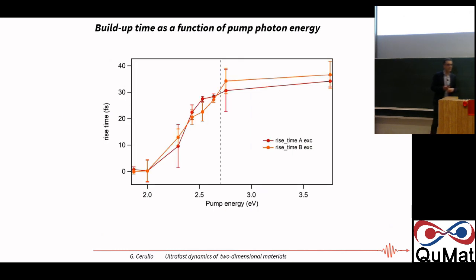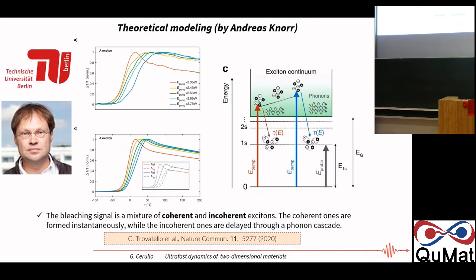So we can really make a graph of the build-up time of the exciton bleaching as a function of pump photon energy, and we see that it rises until it nearly saturates at something around 30 to 40 femtoseconds. So to understand this, we asked for the collaboration of the group of Andreas Knorr in Berlin, who modeled our experimental results, considering that the bleaching signal comes as a mixture of coherent and incoherent excitons.